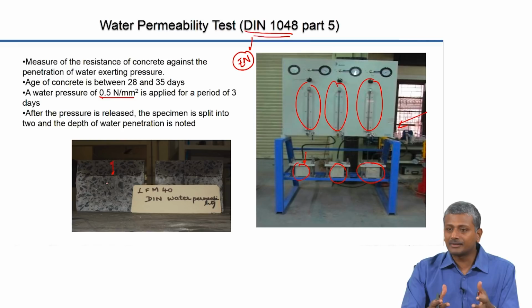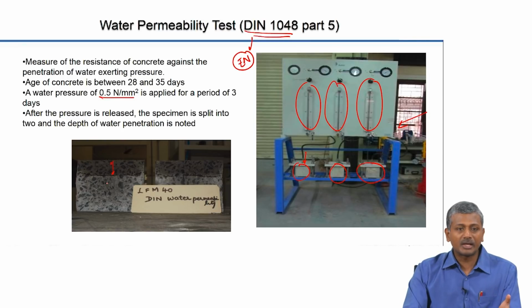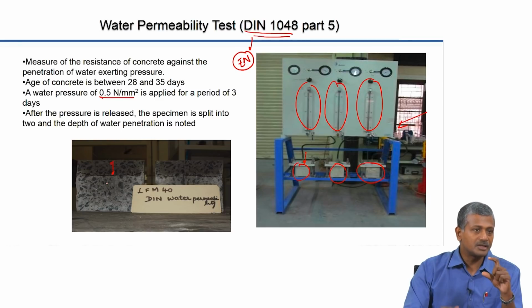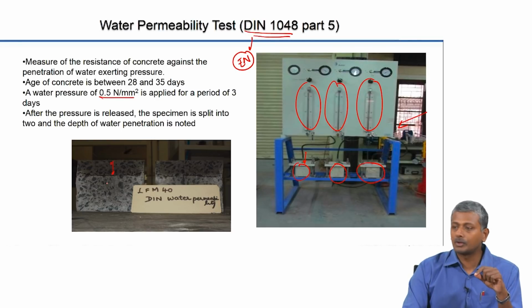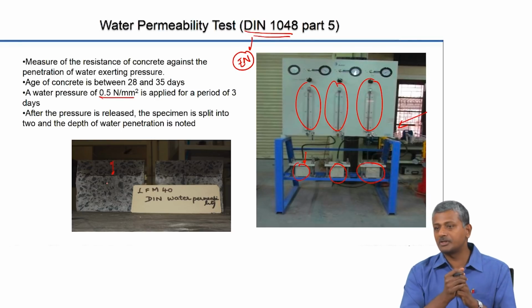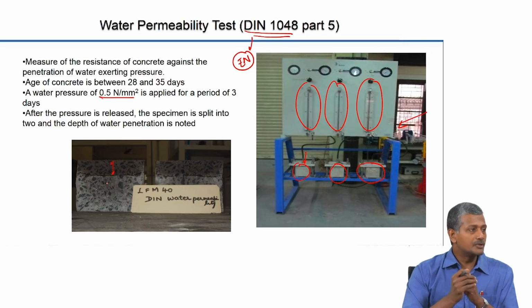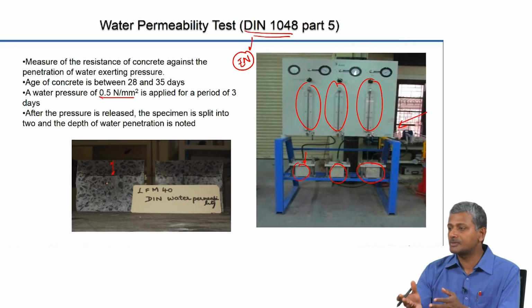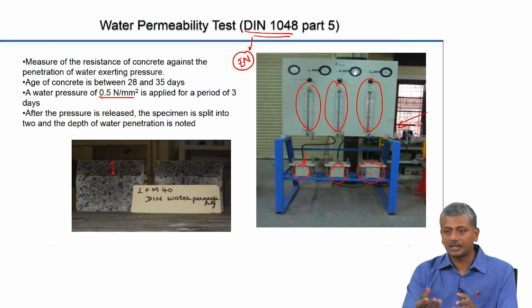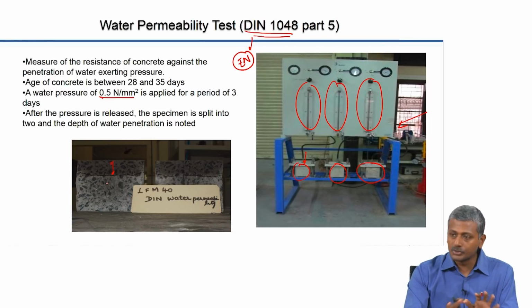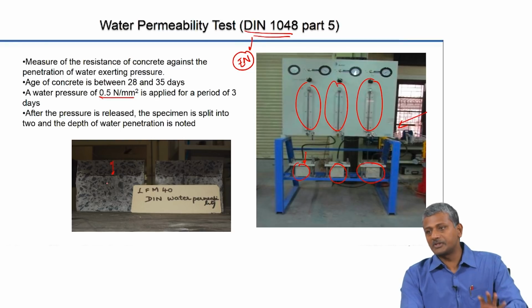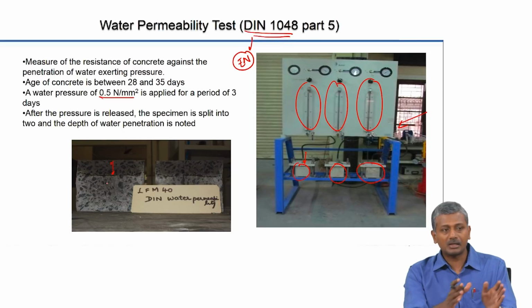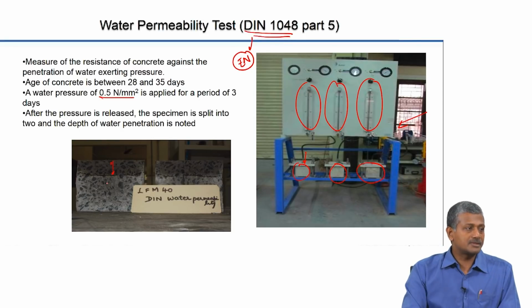For concretes that are having lesser water cement ratios, it's quite easy to get this result, because you will see a clear band of water moving through the concrete. But for concrete with high water cement ratios, this can actually get quite difficult. So in those cases, you might want to subject your concrete specimens to some preconditioning. That means you dry it for a certain period of time and then do the test. But for the most part, this test method is prescribed for concretes without any preconditioning. That means you directly take it from the moist condition and test it.